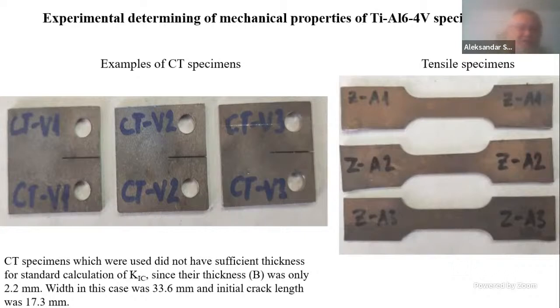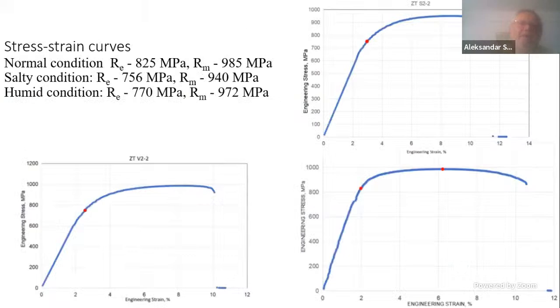Here at the bottom, there is text explaining what I just told you about KQ versus K1C. So we covered that. Now you can see the results for stress-strain diagrams, and you can see that 7-8% reduction of yield strength, less than 10%, is typical for the salty condition and almost the same for the humid condition. But the salty condition, as you will see, is also the worst case for fracture mechanics parameters.